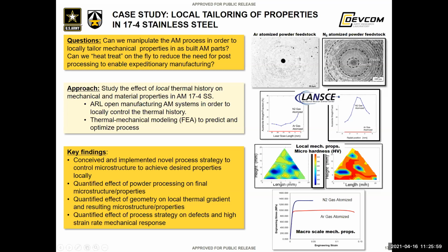And then we also used this to look at critical scan length. We generated these cones of a certain length, and then decreased them going up to the top. We worked with LANSCE, the Los Alamos Neutron Science Center, which I'm sure you guys probably work with at times, to characterize the residual stress as well as the atomic weight fraction of austenite versus ferrite through the height of these objects. We found that with laser scan length, the argon gas atomized had no austenite retained. However, there's a significant critical scan length, which if you're under, actually has a significant increase in the amount of austenite retained within your part.